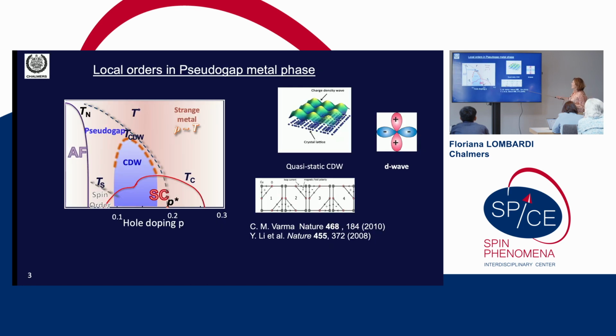The thing is, as I said, that the parent compound is an antiferromagnetic insulator, but then you add oxygen in the chains and the superconductivity sets in. You see here the dome. But close to the antiferromagnetic insulator, you have a phase that is called the pseudo-gap phase, where you are missing states at the Fermi energy. And then you have a pseudo-gap that is doping dependent. But within this pseudo-gap, you have also other local orders.